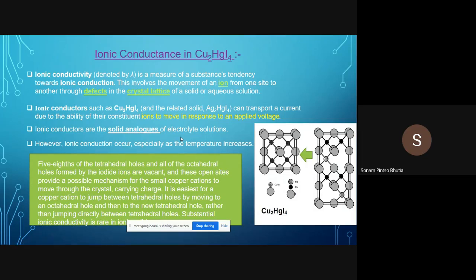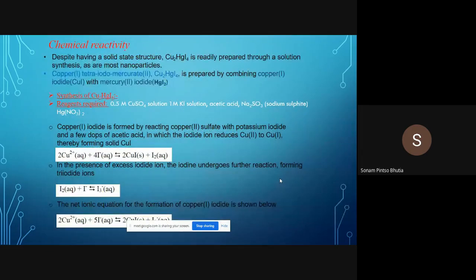The ionic conductor Cu2HgI4 is a solid analogue of the electrolyte solutions. However, through measurement of the conductivity, we found out that the conductivity of the compound increases as we increase the temperature. The main reason was that when we heat the compound, the lattice changes from a tetragonal to a cubic lattice. It was found through X-ray crystallography that 5/8 of all the tetrahedral holes and all of the octahedral holes, which were previously filled by Cu+ and Hg2+ ions in the tetragonal, are now vacant in the cubic, which leads to the free movement of the Cu+ cations, hence increasing the conductivity of the overall compound when it is heated. So we'll now move on to the next part, which is the chemical synthesis of the compound.